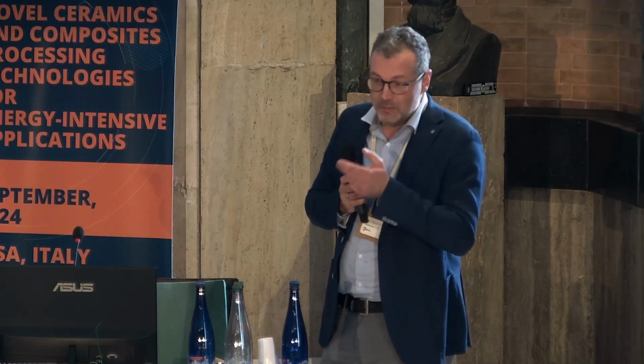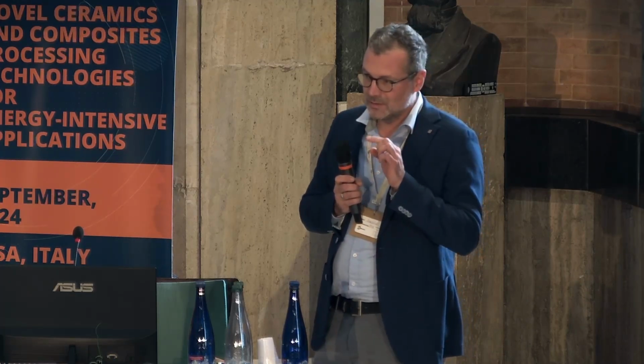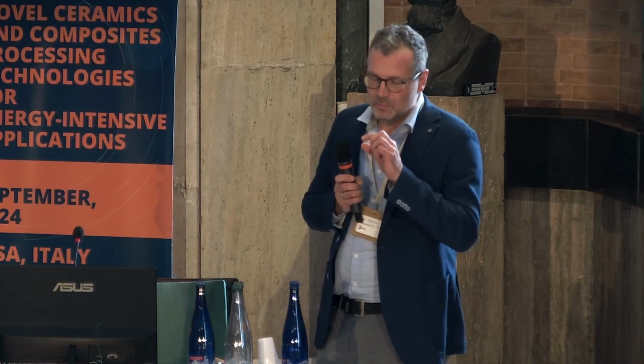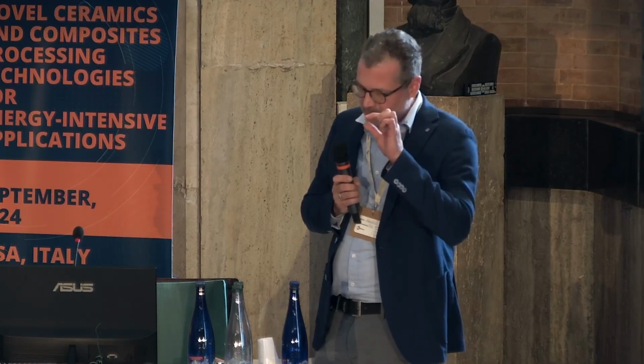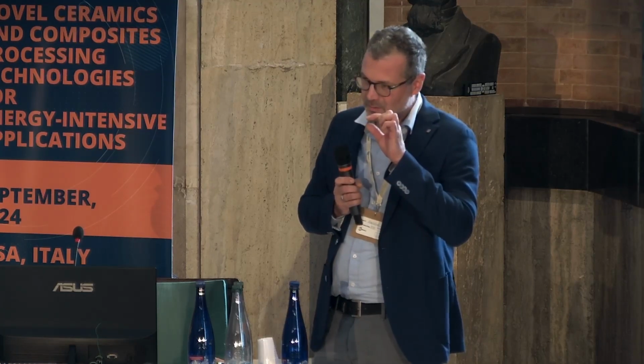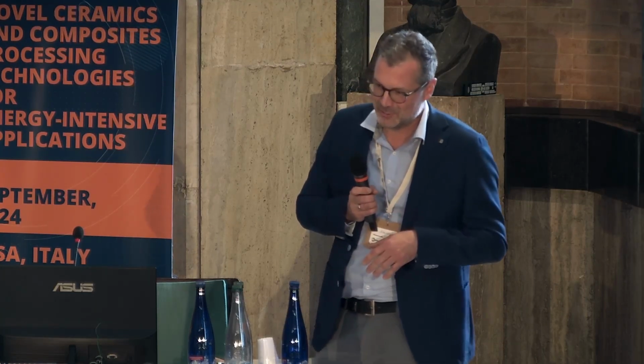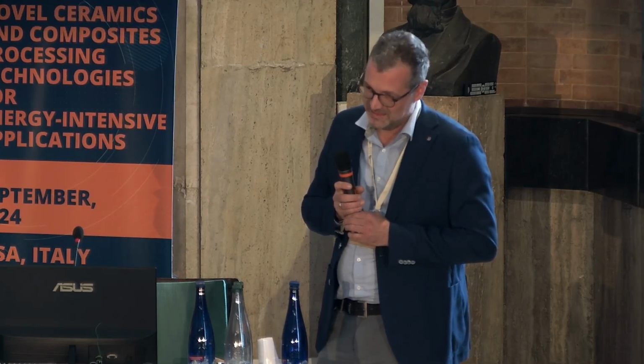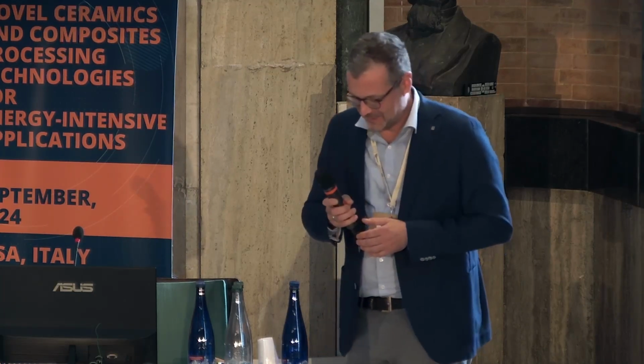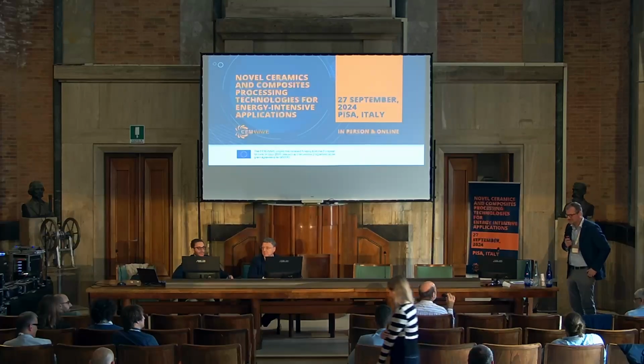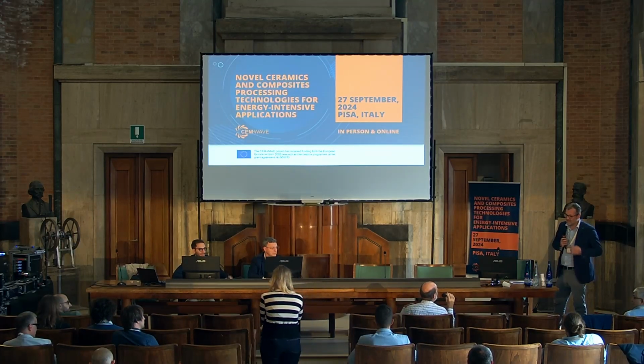And if you are interested in extremely small microscale microstructure in the 3D volume, we really have to cut small pieces out, be careful that we do not damage the microstructure further, and then we could do high resolution microstructure. So in this case, it's a destructive testing, not non-destructive. Exactly this. Yeah. Thank you very much. Yeah, it's not so easy.